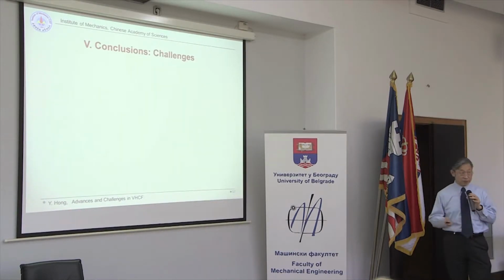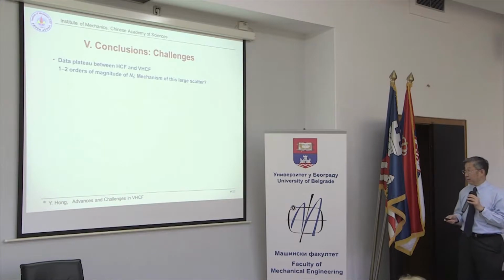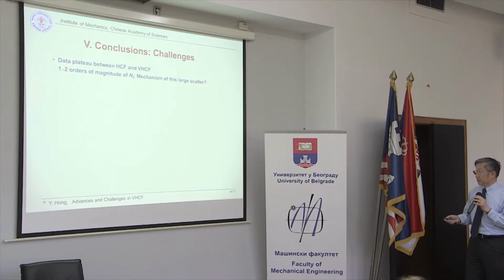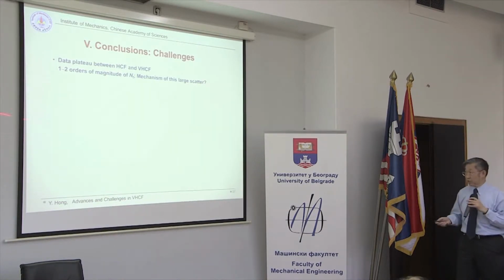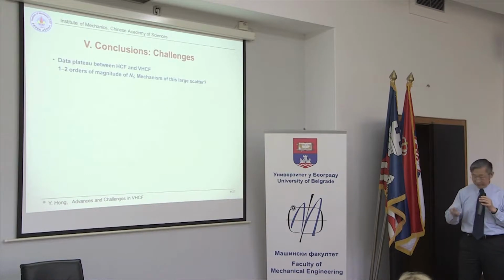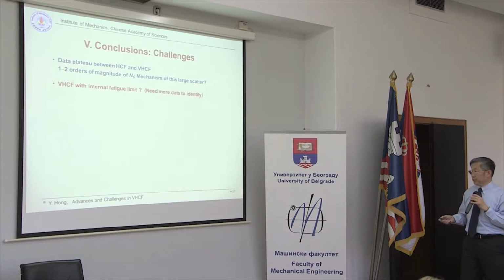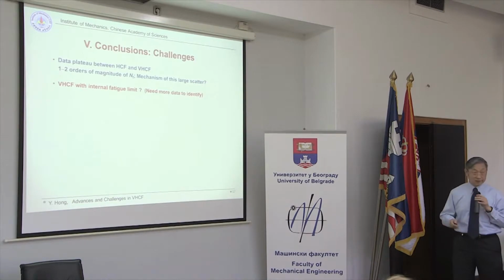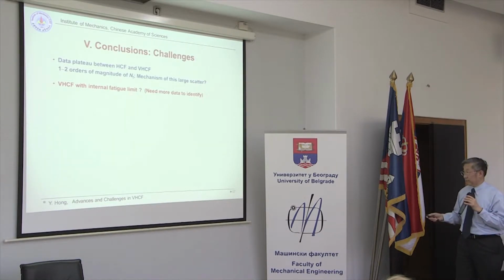And then we have some challenges or some unknown questions. And also I think I put 9 points there. The first is the data scatter between high cycle and very high cycle is quite a large range. It could be one or two orders of magnitude. So what's the mechanism? And the second point is very high cycle fatigue is kind of internal crack initiated, and we may say there's also a limit for internal crack initiation fatigue. We still need more data to identify.